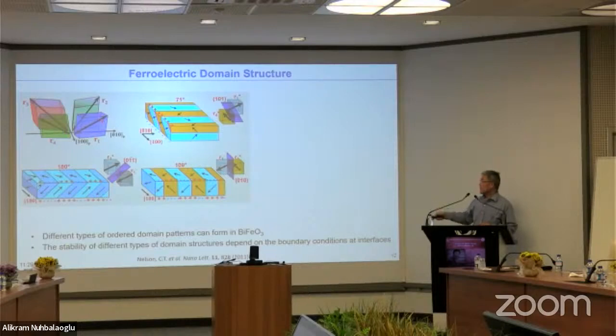Overall, in the cross-cut material, you can see three different kinds of domain structures. With the polarization changing directly by 180 degrees, that's like an interface, a steel ferroelectric domain wall. This is a 109 degree polarization rotation. This is called a 109 degree domain wall, or a 71 degree change of the polarization direction. This is called a 71 degree domain wall.